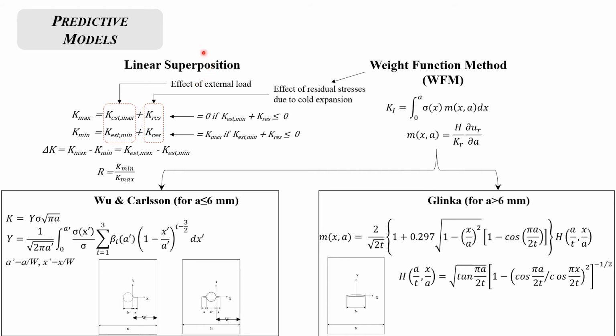By linear superposition between the stress intensity factor due to the applied load and the residual one due to cold expansion, the actual delta K is calculated, setting K minimum equal to 0 if it is negative. Then, using the parameters of Forman's law, we tried to predict the crack growth rate for the expanded specimen. The stress intensity factor due to residual stresses induced by cold expansion has been evaluated by means of the weight function, given by Wu and Carlson and Glinka for crack length smaller or greater than 6 mm, respectively.